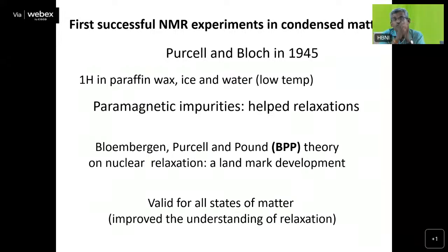Later it was observed that the paramagnetic impurities present in these samples helped relaxation, and this relaxation helped to measure the signal from the sample. That is why they could get the signal.